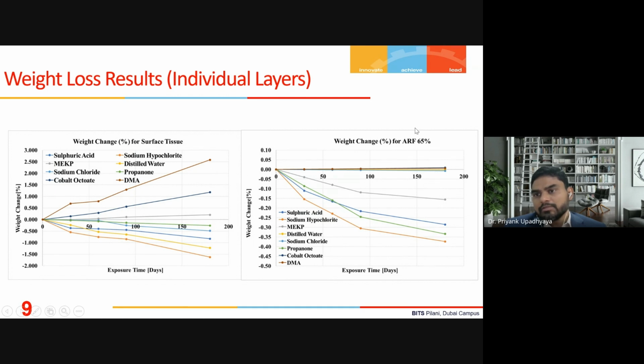Now this one, ARF 65%, is an adhesive that was prepared only for this project because we wanted to recycle the glass fiber that we are using in the whole project. So this ARF is basically the waste generated during this project. We are chopping that waste into small fine particles and mixing it in some adhesive so that we can improve the efficiency of the load transfer while joining these components. We tested the ARF layer individually, and the weight loss is much lesser compared to other layers. Other layers are going around 1 to 1.5%, but in this case, the weight loss is only about 0.35 to 0.4%.